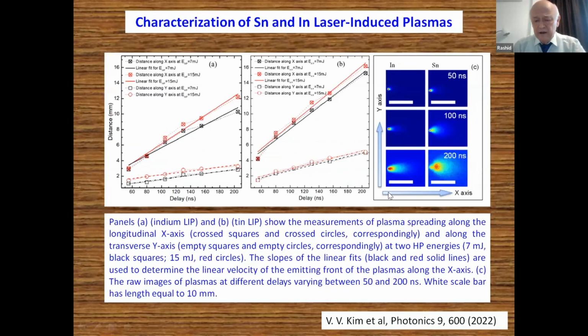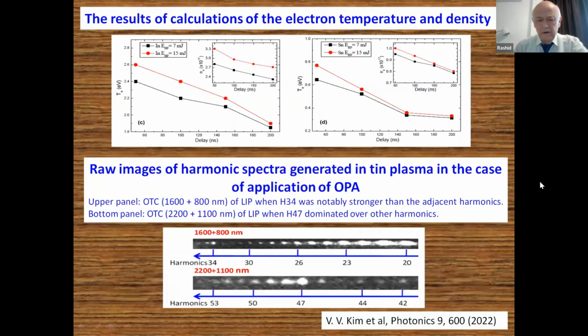How did we do this? As I have shown in previous cases, we analyzed the dynamics of plasma spreading in the case of indium and tin, and found the optimal conditions. It was around 100 nanoseconds, the delay between the picosecond heating pulse and the femtosecond driving pulse. At these conditions, we found the best conditions of high-order harmonic generation. We also, using spectral characterization of plasmas, analyzed the electron temperature and concentration of those plasmas and found the optimal delays for those parameters,